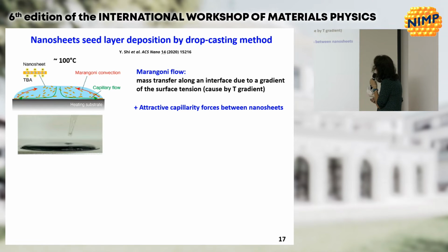The second method is quite recent. It was published last year, actually, by the group of Professor Sasaki in Japan. And they have shown that it was easier to put a droplet of the solution on the substrate, which is on a hot plate at around 100 degrees. And they have shown that there are different processes inside, a Marangoni convection, which is a mass transfer along an interface due to a gradient of the surface tension of the liquid. And here this is caused by the temperature gradient. Also, this is combined with attractive capillary forces between nanosheets.